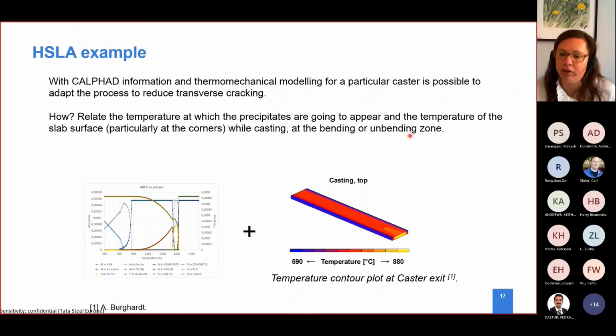If we avoid those areas, we are avoiding the areas that will most probably be in the ductility trough. Therefore, they are the most prone to cracking. And therefore, if I avoid those zones, those temperatures, I avoid cracking. So simple is it.